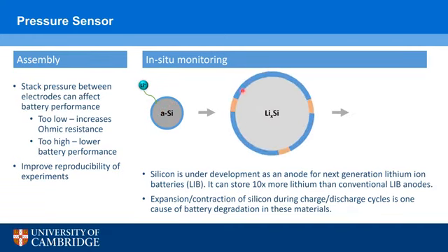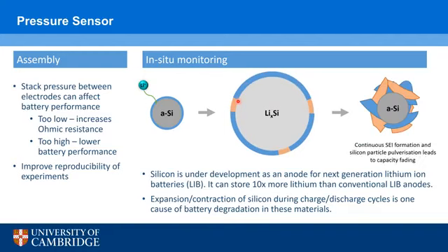This SEI layer cracks and exposes fresh silicon surfaces, where more electrolyte then reacts and forms a new SEI layer. And over multiple cycles, we get this expansion and contraction that leads to continuous SEI formation, and this leads to the eventual pulverization of the silicon particle, which leads to capacity fading and the eventual failure of the battery.